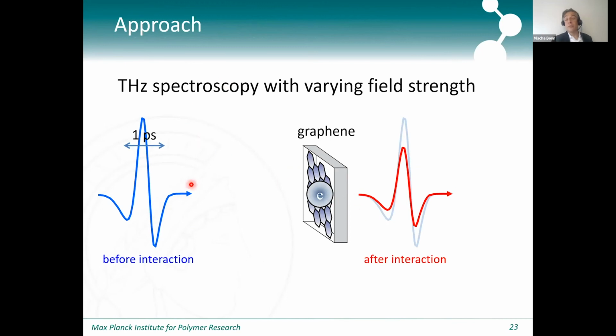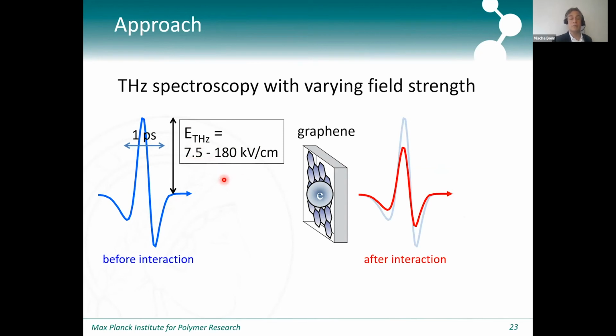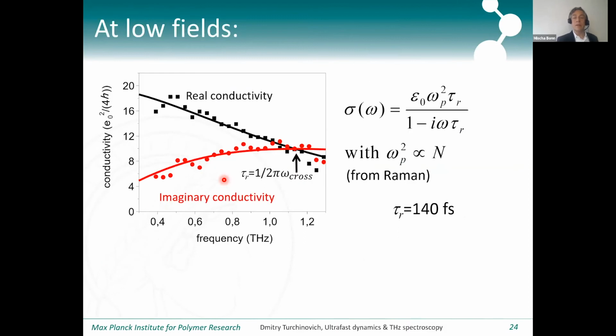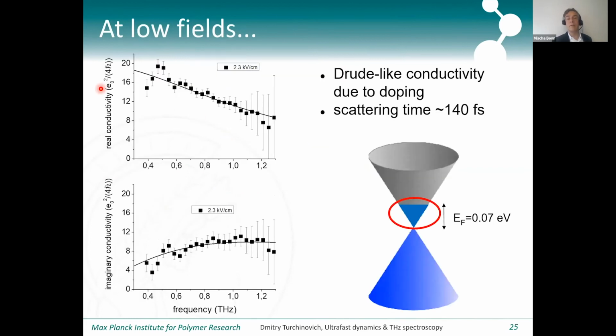Okay, so we're going to do the experiment that I told you about. We're just going to transmit this terahertz pulse through the doped graphene and look at what happens as it comes out. And we're going to change the terahertz field strength from a few to a few hundred kilovolt per centimeter. So again, this is the low field result that I showed you already. And now I show you the same trace, but to avoid a very busy graph, I've separated the real from the imaginary conductivity. And so here you can see at a few kilovolt per centimeter, we have this Drude-like conductivity with a scattering time of about 140 femtoseconds.